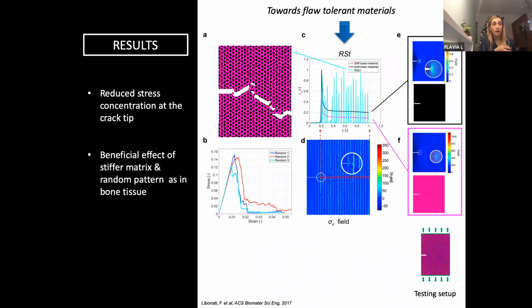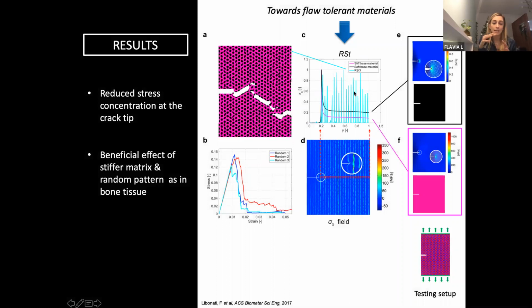And here we notice how this material actually is reaching flaw tolerance, in the sense that if we look at the stress field from the crack tip to the far field, we can notice that the peak stress is reached not only at the crack tip, but also far from the crack tip. So in this case, we are aiming for flaw-tolerant materials, where the material doesn't feel the main crack anymore, but you can have different positions of energy dissipation, which all can contribute to a toughness enhancement in the overall material.